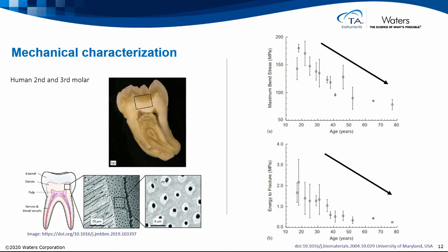And energy to fracture, which is sort of its capacity to resist loading. Another way to measure it is also reduced significantly. In this case, even more than half, reduced by the time you're 50 or 80. So this is one way to look at these results. But if we sort of back up a little bit, we'll see.